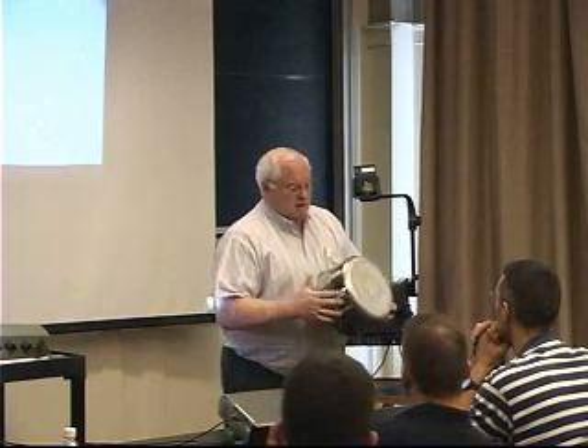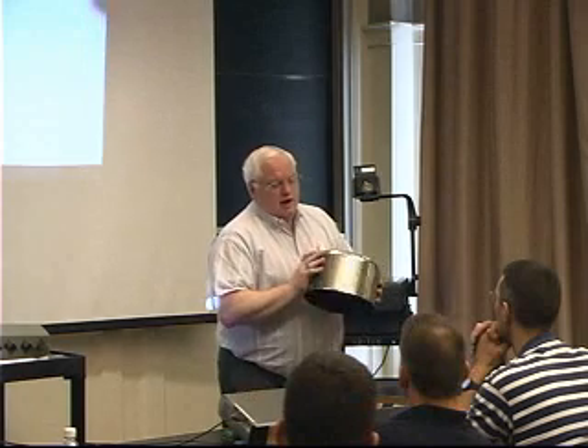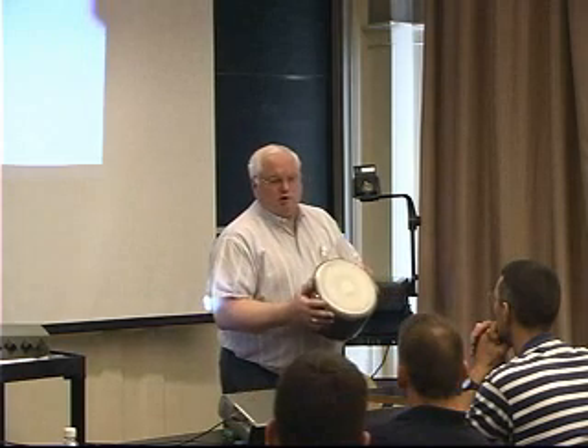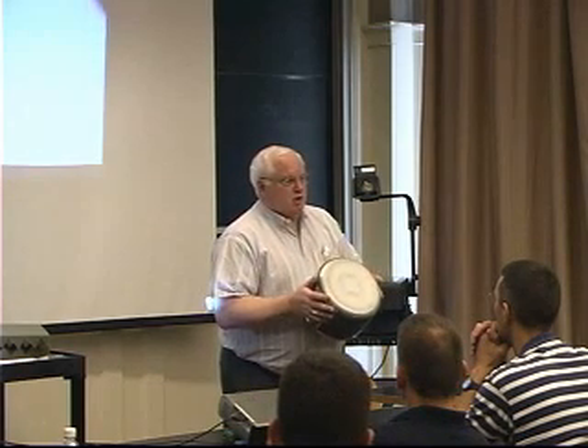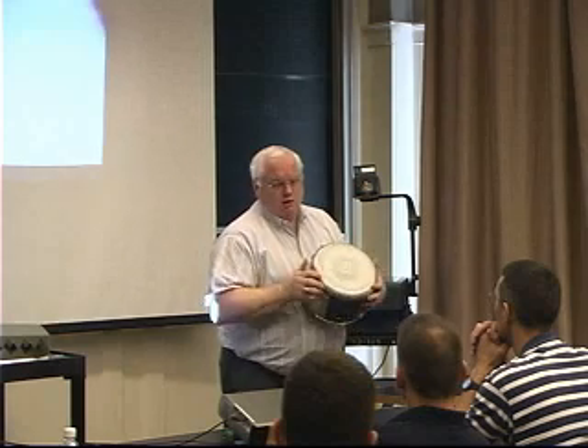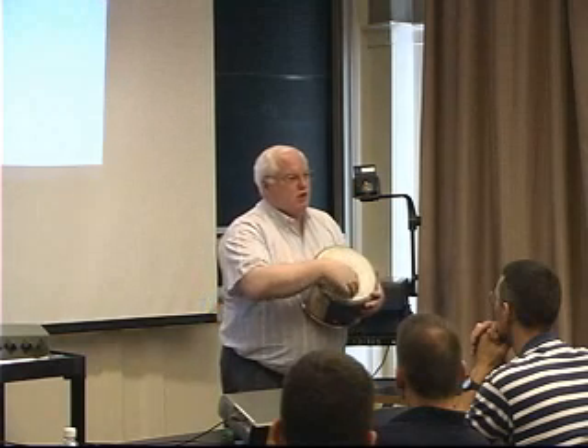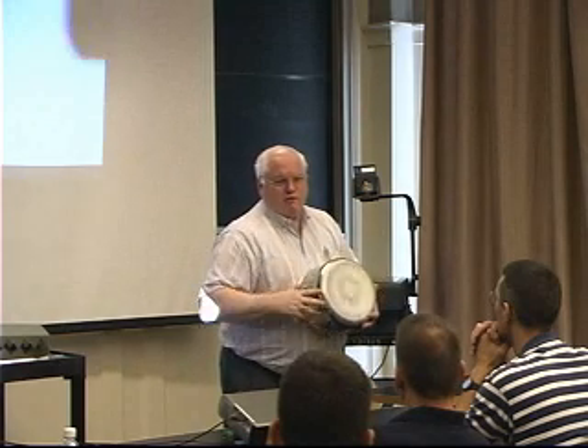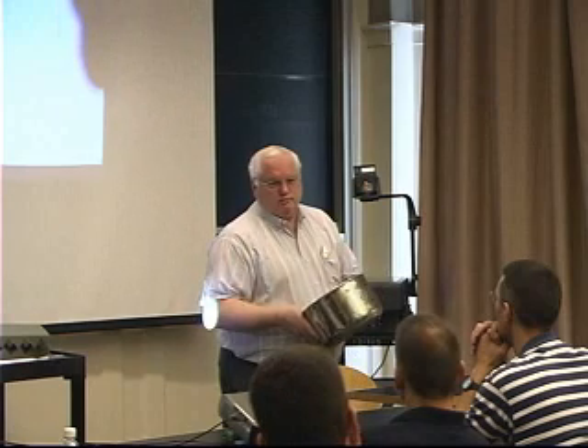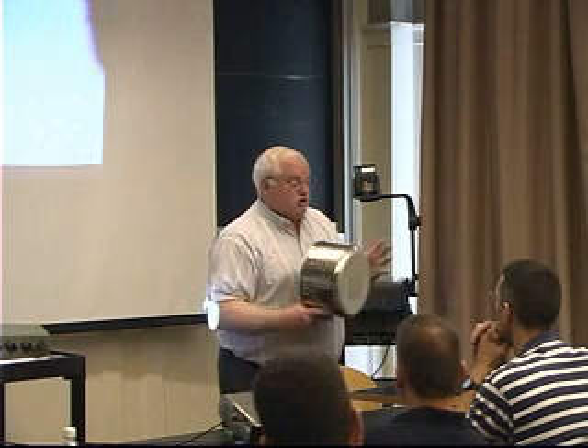So it turns out they didn't know it. I had to explain to them it was a lousy way to get a cold weld, but they probably only wanted 10 to 30% bond. They probably wanted some voids in there to allow for the differential coefficient of expansion on a microscopic scale. So that's cold welding there.